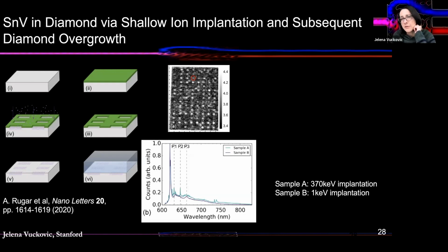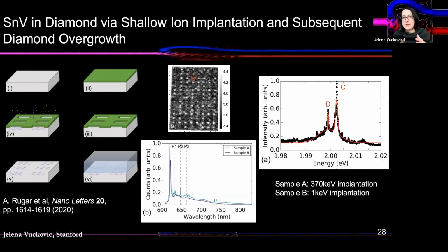For diamond, we've been collaborating with the groups of Nick Melosh and Zhi-Xun Shen at Stanford. And of course, the burning question is how do you incorporate them at the desired positions and have exactly one quantum emitter at the desired position and so on. And this is something that had not been possible before, because to incorporate them, people would typically use high energy electron beams or ions, in order to bombard diamond and incorporate these impurities at the desired places. But then it's very difficult to mask the material, and also this high energy implantation damages diamond, and that way introduces additional broadening and degradation of the properties of the color centers.